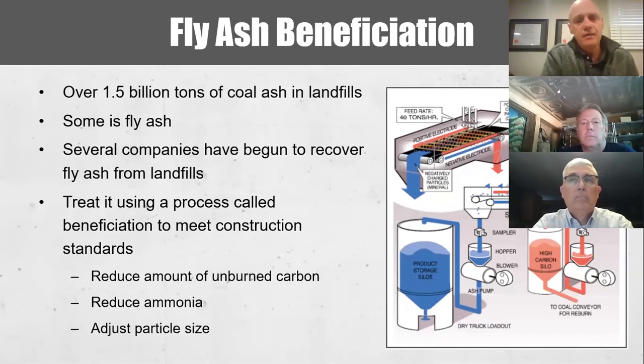And so there's a valuable material that some companies are now actually mining, beneficiating in some way, which means it does need some processing, usually to dewater the ash, but also, in some cases, it may be out of spec to be used in concrete. So things like reducing the amount of unburned carbon, reducing ammonia, and adjusting particle size through different processes. So I think this is a huge opportunity for our industry. 1.5 billion tons of coal ash or more in landfills could be a source for literally decades.